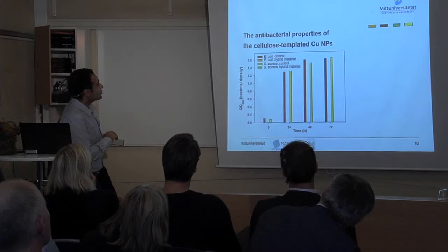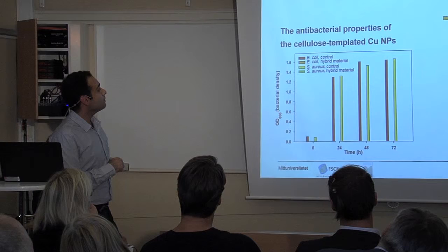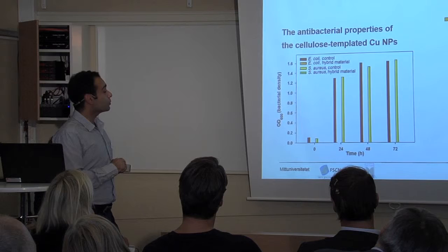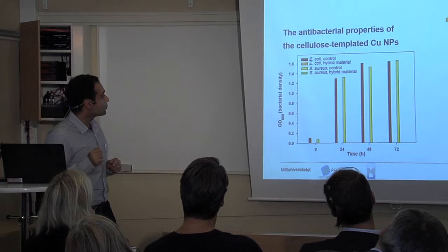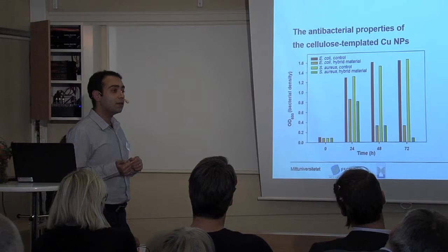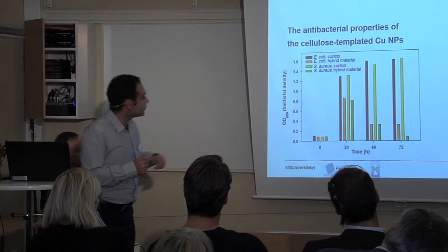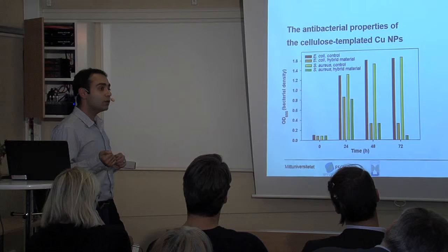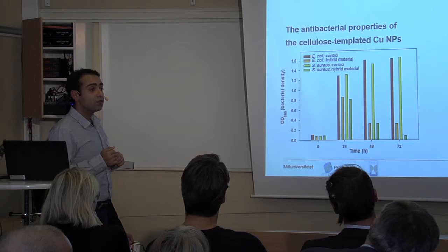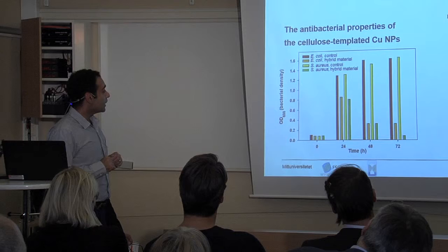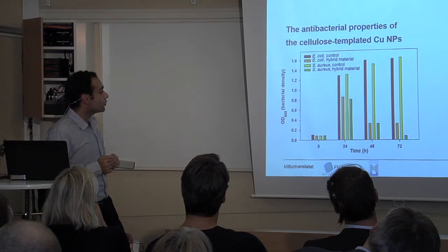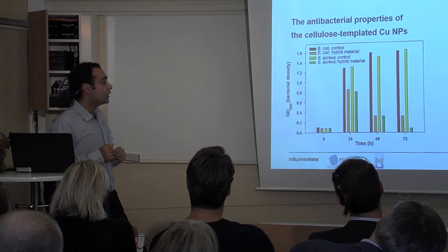As a possible application for the synthesized hybrid material, we examined the antibacterial properties of this material for both gram-negative and gram-positive bacterial strains. Our results clearly show that bacterial growth was inhibited in a suspension containing the hybrid material. After 24 hours, there is almost a 40% decline for both gram-negative and gram-positive bacterial strains compared with their control samples. After 48 hours, there is even more decline in bacterial density compared with control samples. After 72 hours, there is almost an 80% decline in bacterial density for gram-negative bacterial strains, and almost 90 to 95% decline in bacterial density for gram-positive bacterial strains.